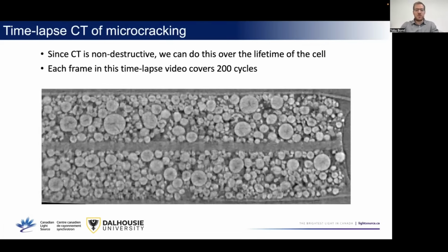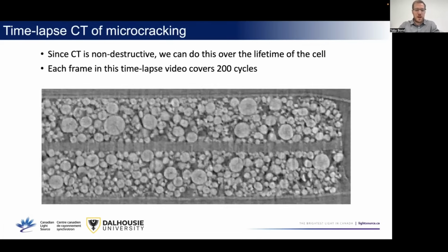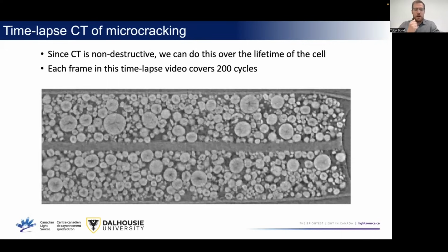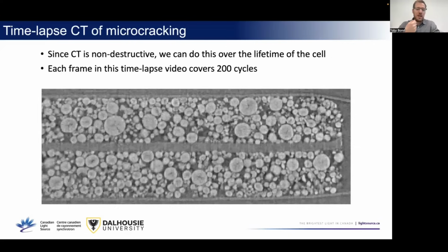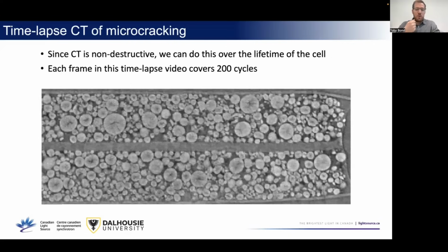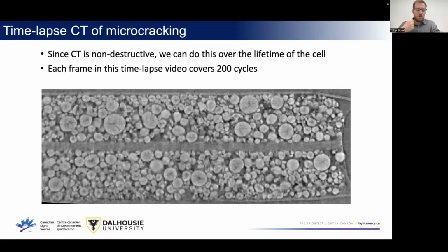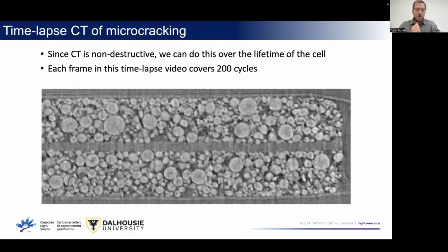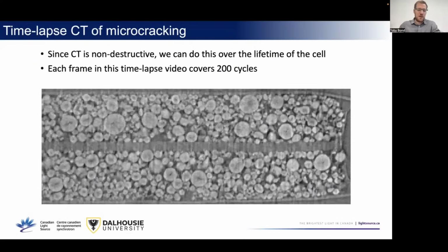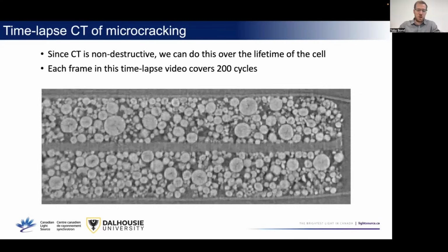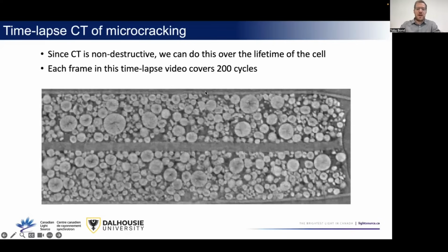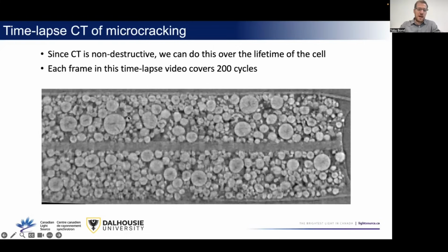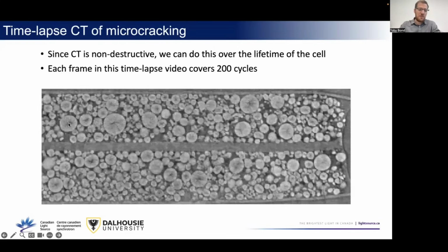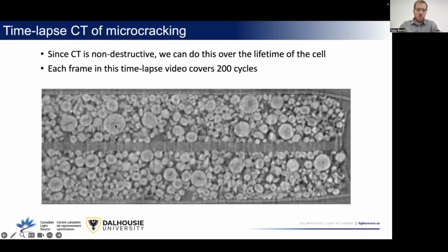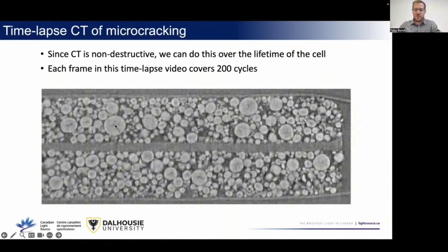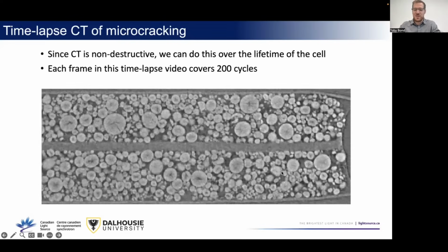So another nice thing that we can do is, because we don't have to take the battery apart, we can actually track this microcracking as it happens over the lifetime of the battery. So this is a time lapse where we took a CT scan every 200 cycles, and there's 6 frames, and they cover 1,200 cycles of charging and discharging. So you can see this expansion, the swelling that I was talking about, and you can see the centers start to get dark and kind of hollow out, and these cracks start to form. So you can actually look at the onset of this process as the battery ages.